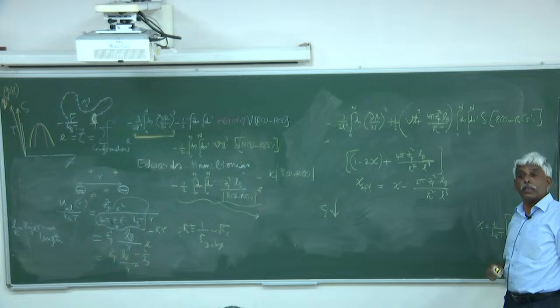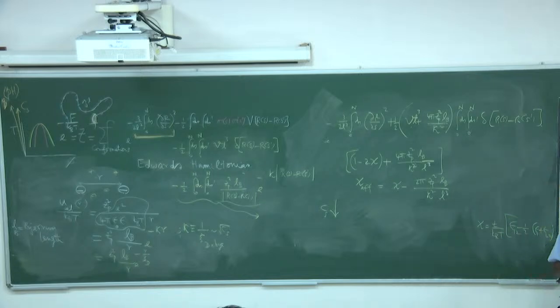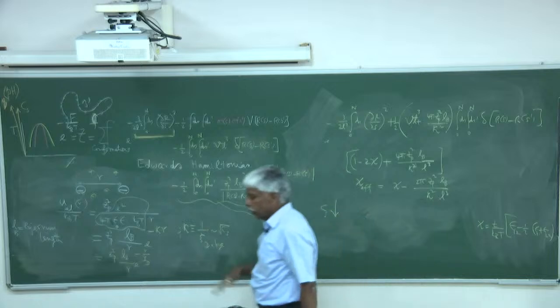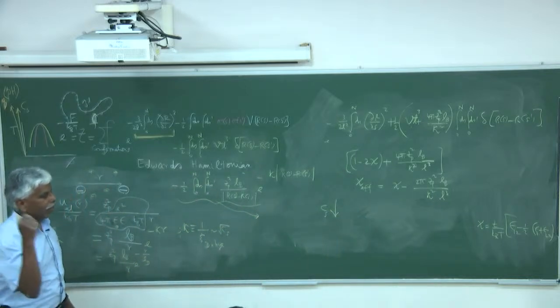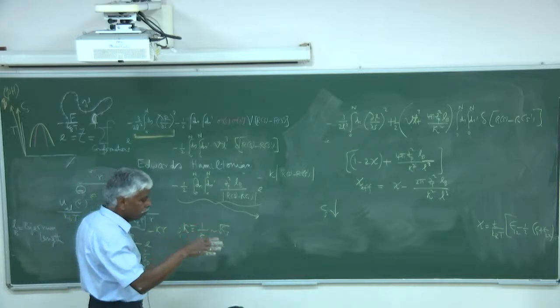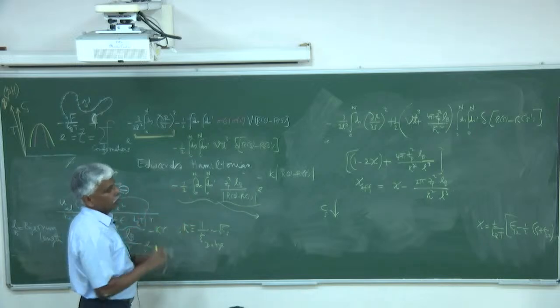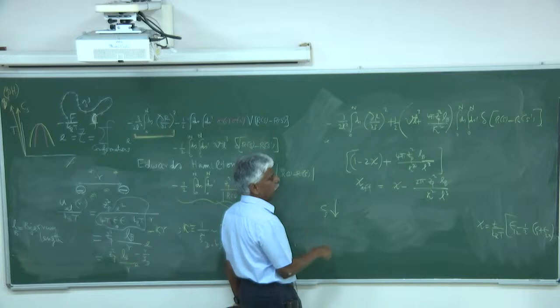Anyway, let us look at salt concentration low. When you lower the salt concentration, kappa square becomes smaller. When it becomes smaller, this whole thing becomes larger. There is a negative sign, so chi gets reduced. What happens when chi gets reduced? Homogeneous, miscible. It makes sense, because when you have larger salt, charges get screened out. When the salt comes lower, the charges are manifest, they repel, so they spread everywhere. That's why they become miscible.